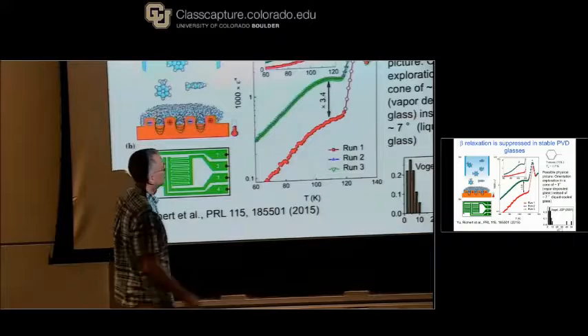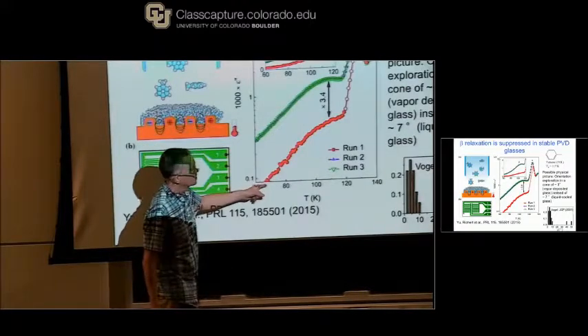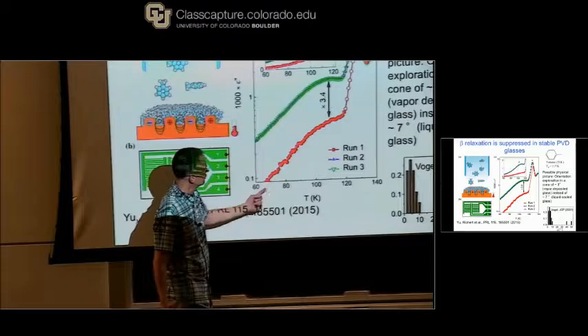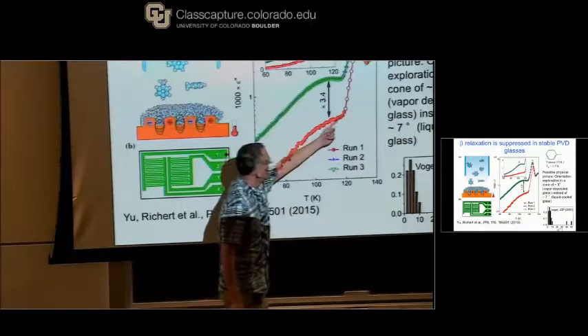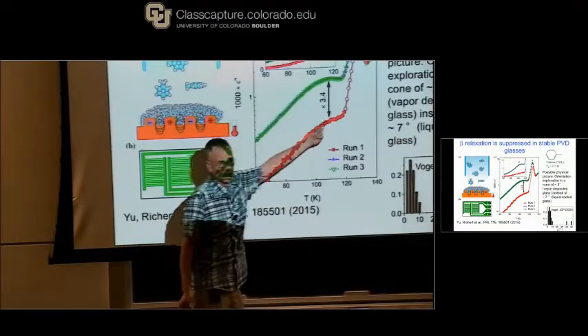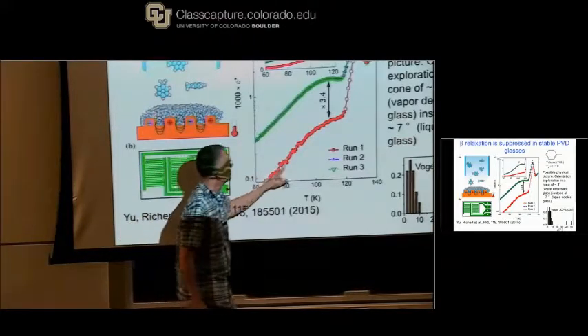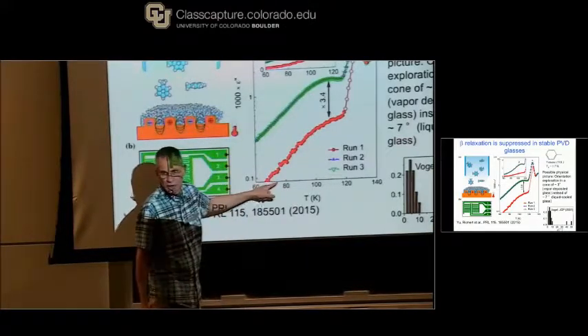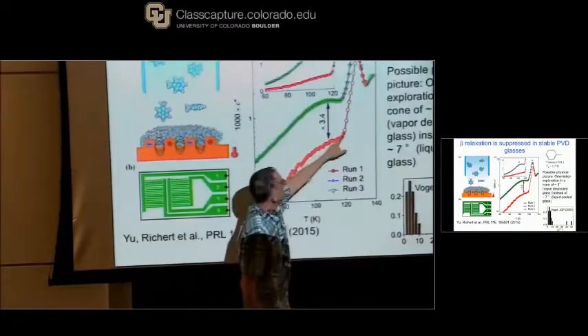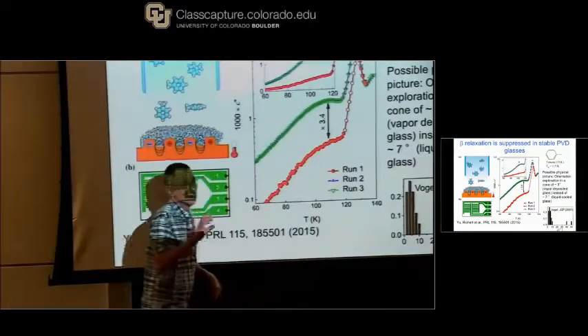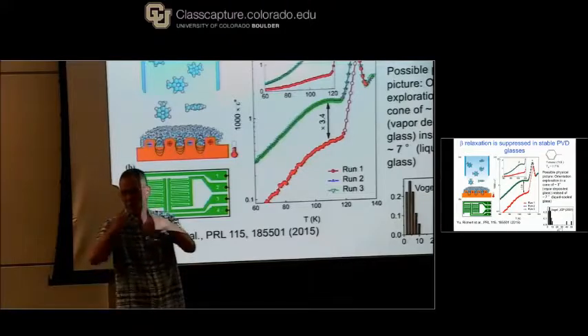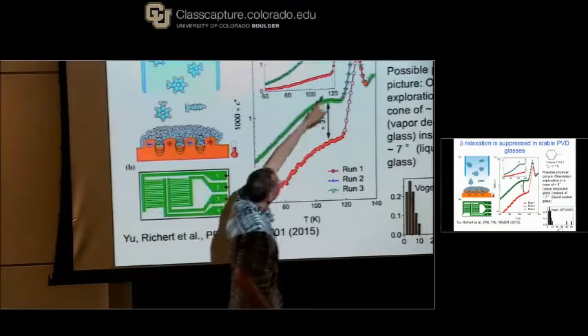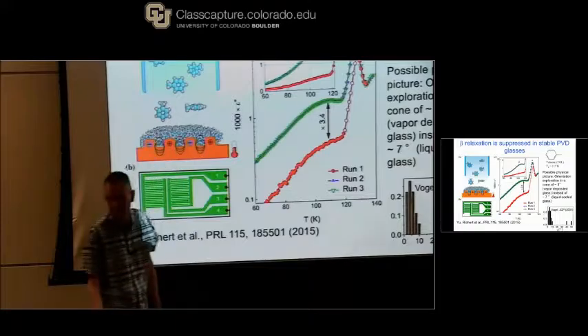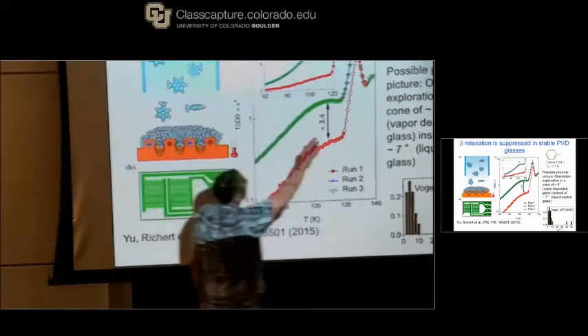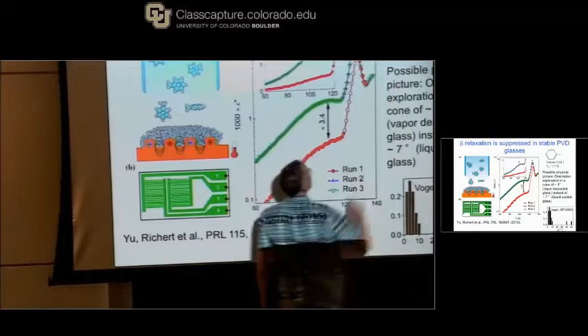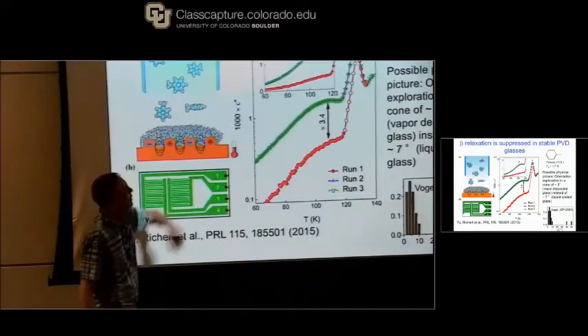And so this is a really stable glass. This is the dielectric loss as we heat it up. Across this regime, this is reversible. So this is deep enough in the glass, you can scan up, you can scan down, you'll always measure this loss. Once you get to this temperature and you get to the open points, the sample is starting to transform into the liquid. By the time you get to the end of the open points, it's completely a liquid. And then this is now the supercooled liquid. So that's what happens in run 1.